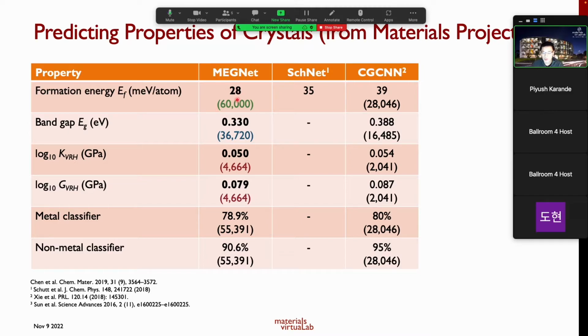Now, I want to focus on a few properties here. If you think about the formation energy, for instance, the MEGNet models that we train can predict the formation energy to a mean absolute error of 28 meV per atom, right? And this is actually on par or better than most of the machine learning models out there for the formation energies, okay?